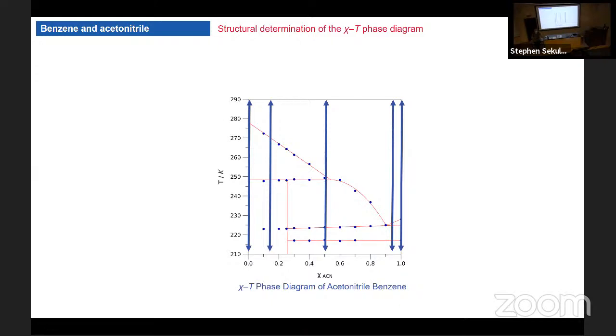There are many different techniques that we can work with. Arguably, the best one is X-ray powder diffraction. The reason why it's the best one: X-ray as a probe is quite fast, so you can be collecting data for a couple of seconds if you use synchrotron radiation. On the other side, powder is easier because you don't need to grow single crystals, large single crystals. The sample preparation is very easy, and the handling of the samples is also very easy.